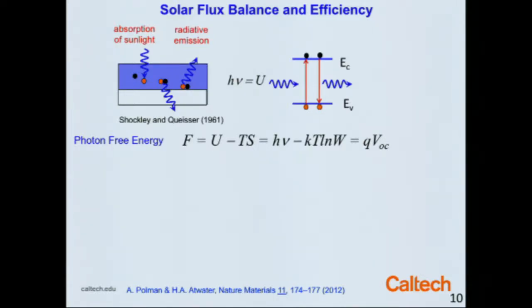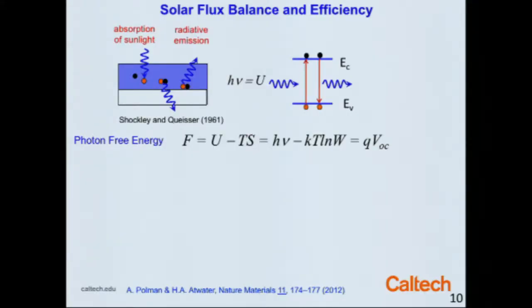But there's another important way of looking at this, which is that photons actually have an entropy as well. This turns out to be an important aspect of thinking about efficiency limits for solar energy. So in fact, what we care about is not the enthalpy ultimately, but the Helmholtz free energy. The enthalpy minus the entropy gives us effectively the photon energy minus what is often a configurational entropy, and that defines the maximum voltage that I can get to.